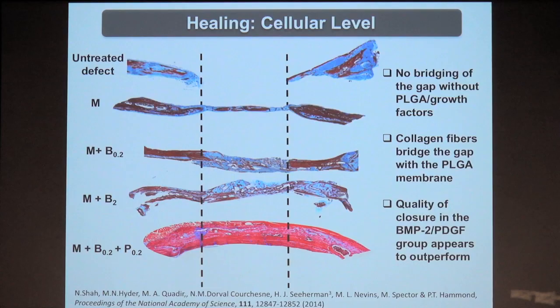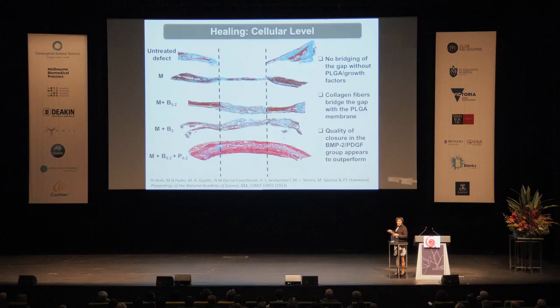But what you see is that there are a lot of defects, and that bone does not look like the bone in the margins, in which we're staining for both the blood vessels and the bone itself. We can see that it looks kind of disorganized and lumpy and not very well formed. When we test the mechanical properties of this bone, it breaks earlier than native bone. So it's kind of a brittle, unsatisfactory bone.